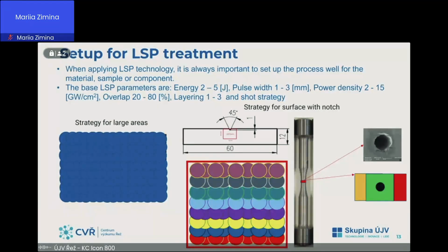The goal of the strategy is redistribution of maximum residual stress, compressive residual stress, to one point or small area. Or we can use only one or three shots for the notch. You can see on the right.